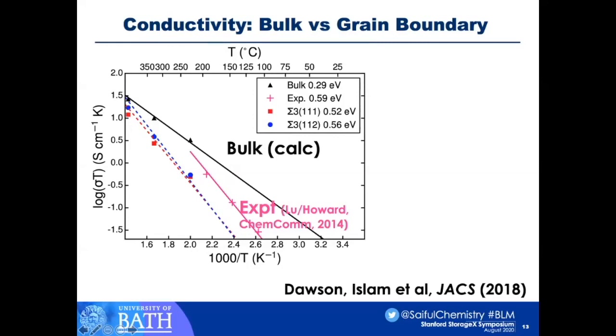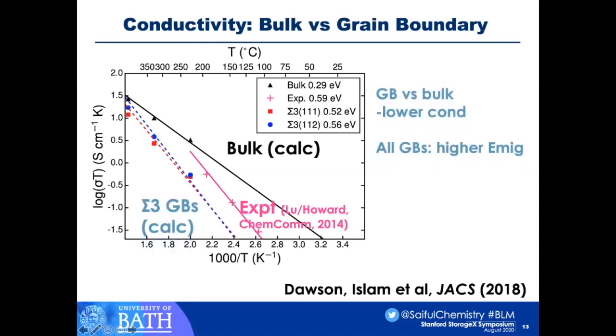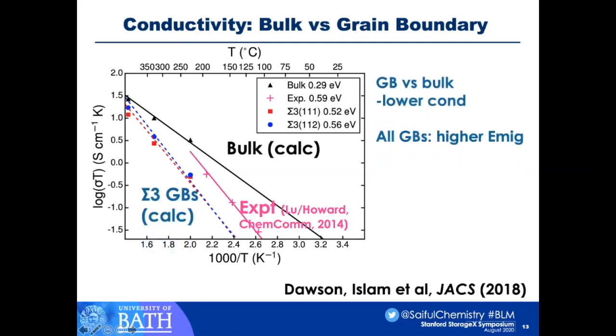So a few things you can see straight away. Our calculated bulk does not accord in terms of slope with the experimental value. In fact, the migration barrier is about 0.3 eV from the bulk, whereas it's 0.6 eV experimentally. The second thing to note is that we're finding that the grain boundary conductivity is lower than the bulk. So this is confirming that we would expect significant grain boundary resistance within these materials, with a higher barrier and a lower conductivity.